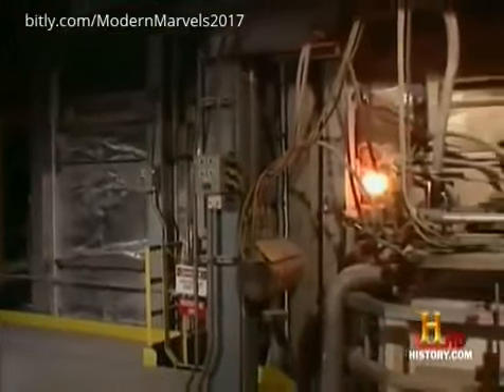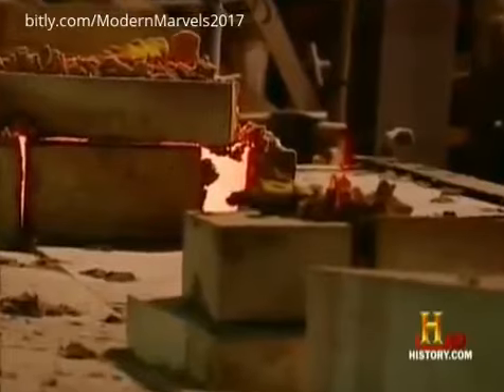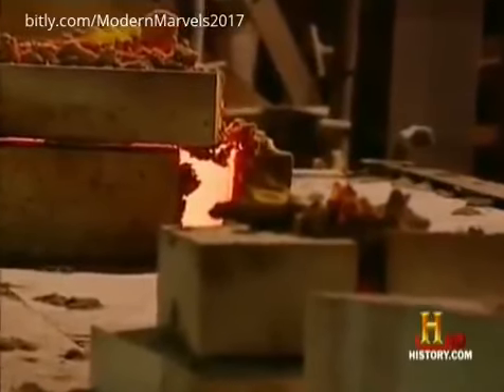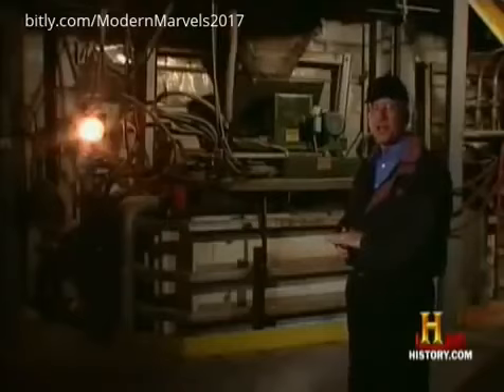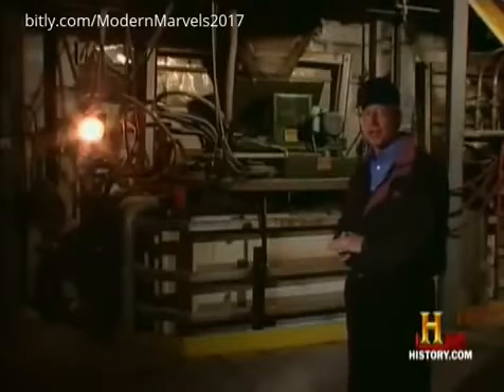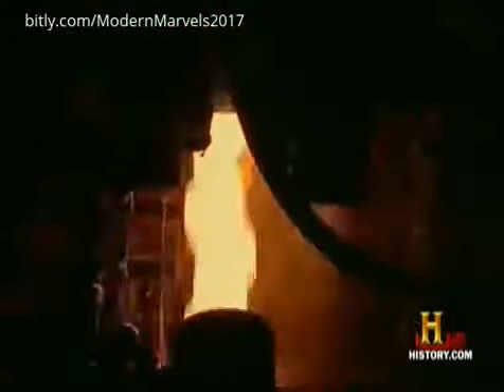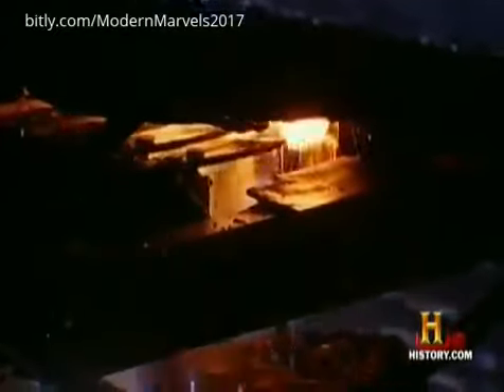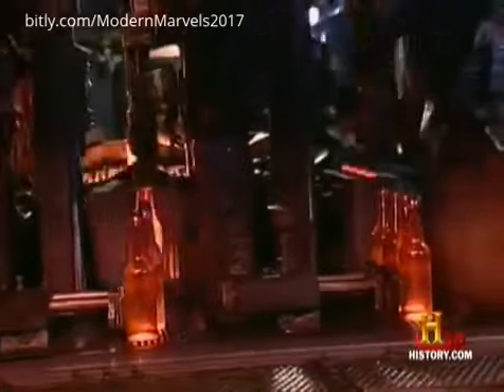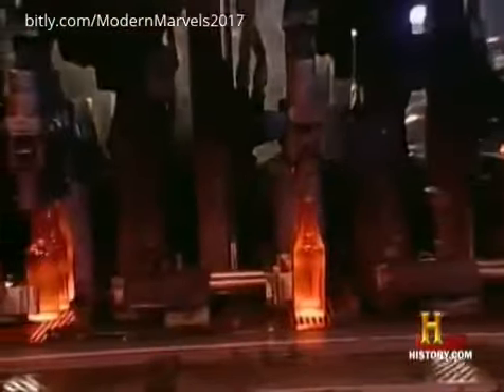The fiery furnace that is approximately 5 feet deep converts the raw materials into molten glass. This furnace consists of high-temperature ceramic brick of many different sizes and shapes and weights. It contains about 500 tons of molten glass at about 2,800 degrees. After the glass is melted in the furnace, it's delivered to the forming machine. The molten glass gets sheared into uniform pieces called gobs, and then blown into the mold shape with compressed air. The glass enters the forming machine at 2,100 degrees Fahrenheit.